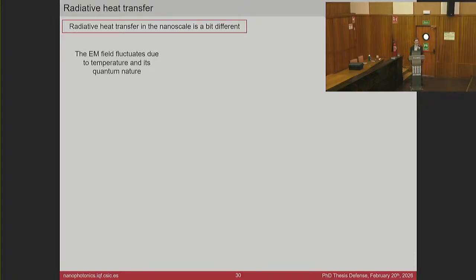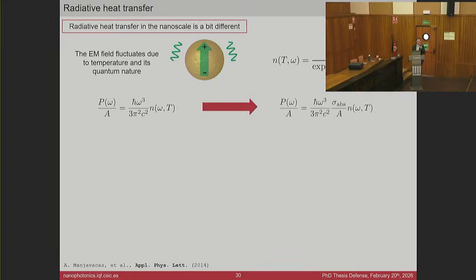Well, we know that the electromagnetic field fluctuates due to temperature and because of its quantum nature. And we have a nanostructure with a fluctuating current. We can understand it classically as an oscillation of charges, and we know that when such a thing happens, it will emit electromagnetic energy, thermal radiation, and of course these fluctuations will be controlled by the Bose-Einstein distribution. Now, while in the macro scale or for extended systems, this gives rise to black body radiation, this is going to be a bit modified in the nanoscale because we now have this ratio of the absorption cross-section to the physical area, the geometrical area of the nanostructure.